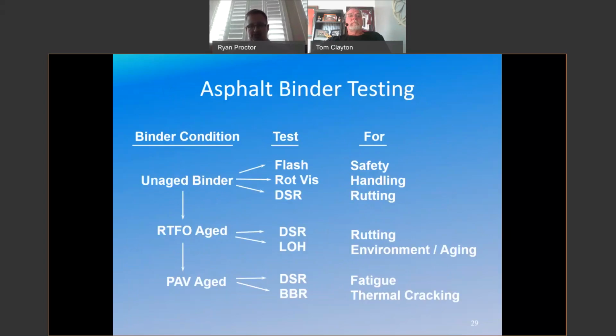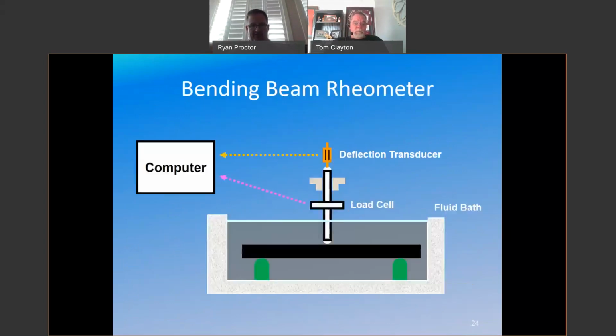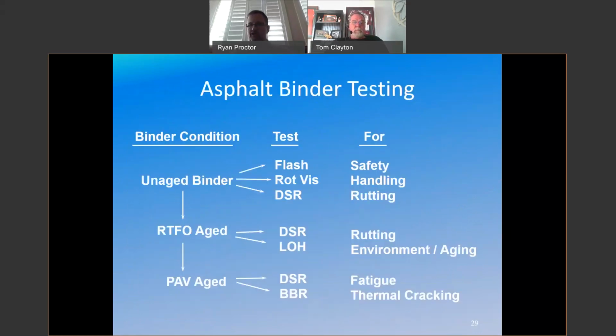All right, I went through this all fairly quickly. I mentioned everything except for one test that's on here. If I go back to that RTFO graph and you think about that carriage that's rotating, we can take an asphalt binder, and it's kind of like running a moisture value on an aggregate or a hot mix sample. We'll weigh the asphalt before we put it in the RTFO, and we'll weigh it after we put it in the RTFO. And the goal of that test is that we don't want there to be a lot of light ends or material that gets burned off in the hot mix plant.